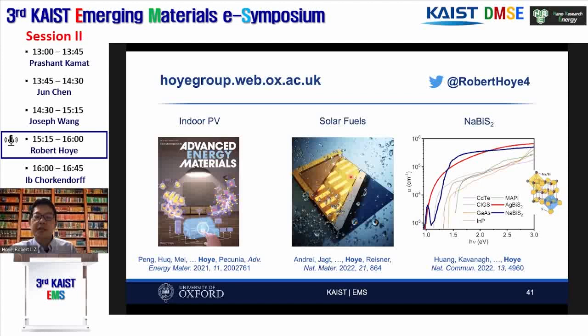achieve bias-free syngas production. And in the last part of the talk, I talked to you about sodium bismuth sulfide, and in particular the higher optical absorption coefficient we get with the material, but also carrier localization. But at the same time, even though we have charge carrier localization, the diffusion lengths we can achieve are still about 100 nanometers, which is greater than the thickness needed in order to absorb sufficient light. So potentially sodium bismuth sulfide could still work as an effective solar energy harvester. So with that, I'd like to thank you for your attention and be very glad to take questions.